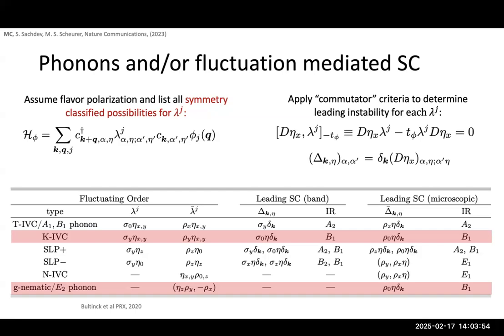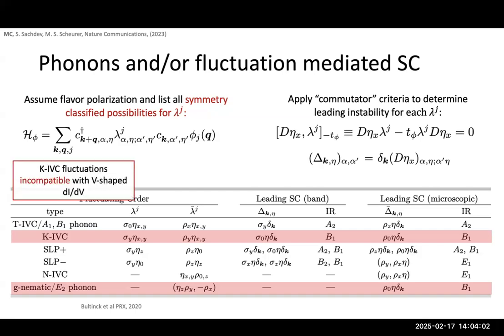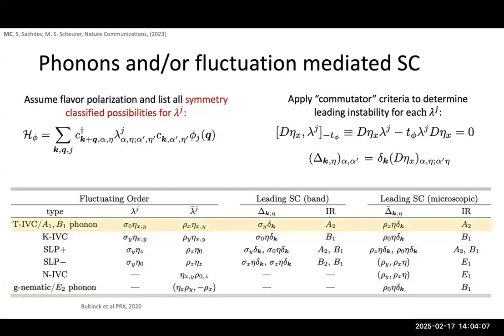So then of these remaining states, can we say something about which of them might be more or less likely? I want to argue that a good state to consider is this TIVC state. And the reason for this is twofold. The first is we actually know experimentally what the order is in the insulator. So we know the symmetry that's being broken near nu equals 2. I'm showing a snippet of the data from the Yazdani group, where they did STM measurements and were able to identify time reversal symmetric intervalley coherent order in the insulator.